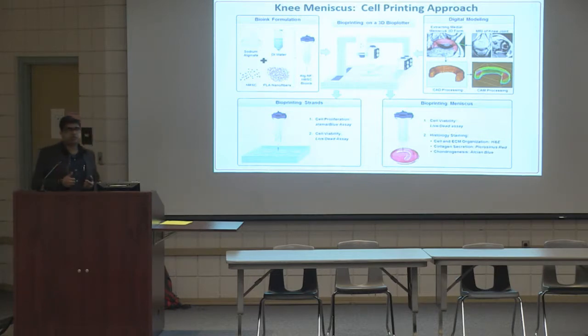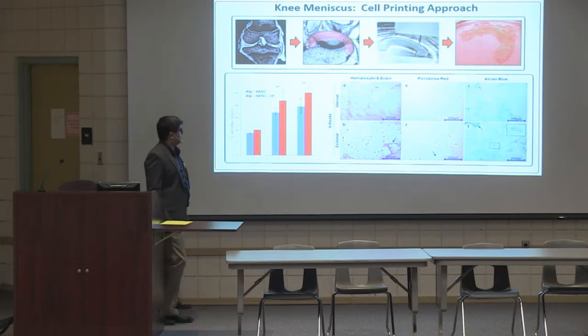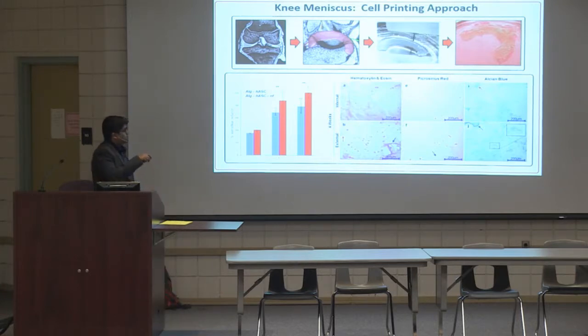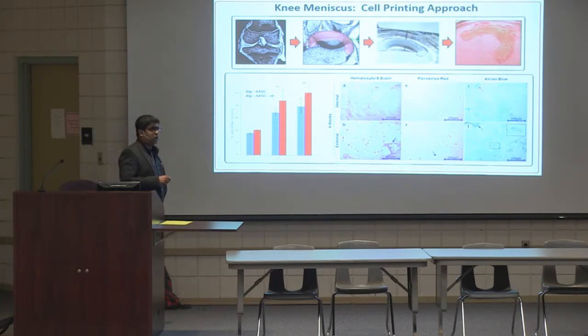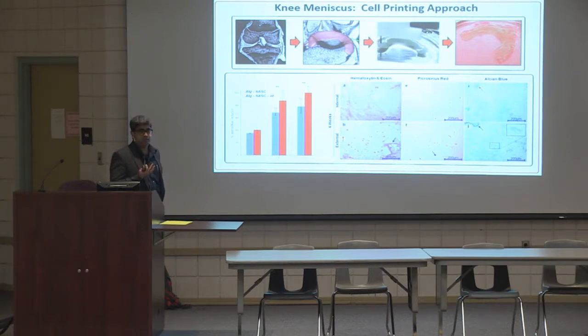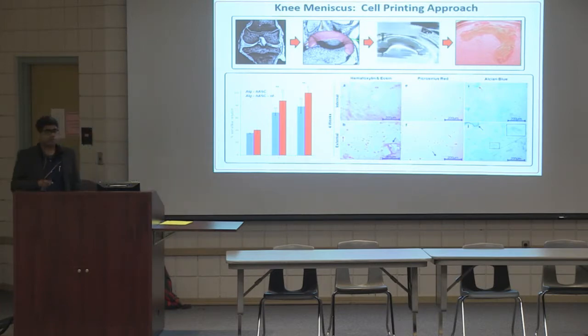These were stem cells. We added the right type of bioactive factors. We wanted to see if they started turning into cartilage or cartilaginous tissue that is found in your knee meniscus. And we got good proof that was happening. Over time, what we noticed was the cells were able to survive and keep growing. But we also noticed that the bio-inks which contained those fibrous nanofibers, the cells actually did better on them. And that was something we had hypothesized because these tissues are fibrous in nature.